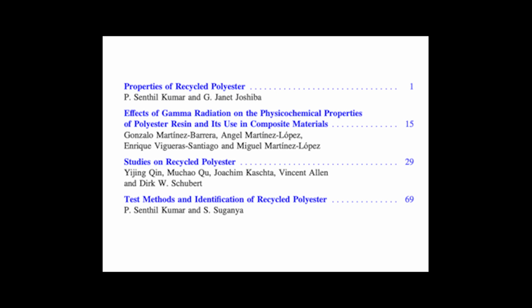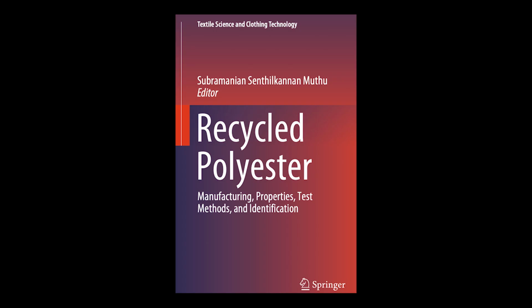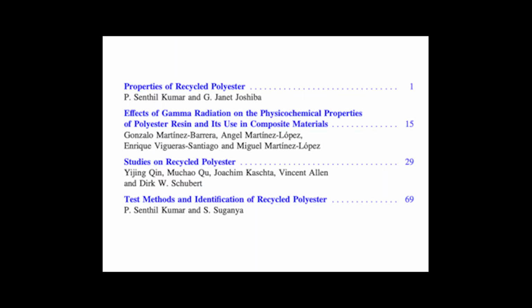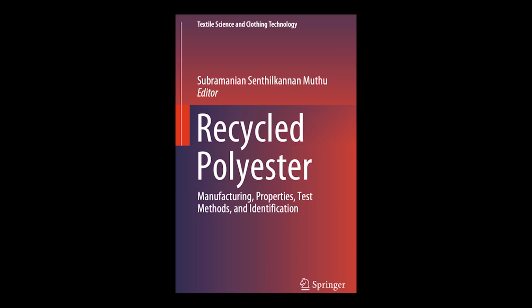30%. Why so high? The researchers directly attributed this severe degradation to the unavoidable contaminants present in that mixed color waste stream. Things like different dyes, maybe residual labels, other plastics, they just accelerate breakdown under heat. Makes sense. They also noted a general trend. Copolyesters, which included both the recycled flakes, rPETA and rPETB, as bottles often use copolymers for clarity, and one of the virgin grades, vPET2, tended to show more thermal degradation than the simpler homopolyesters, like vPET1 and vPET3. Why would copolymers degrade more? Likely due to their slightly lower melting temperatures and perhaps less stable chemical structures compared to homopolymers.